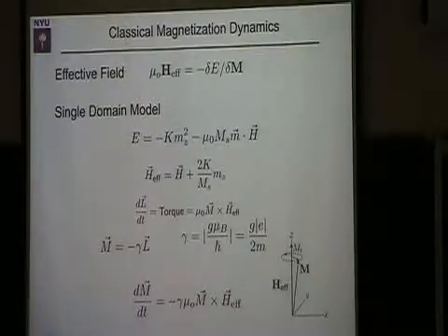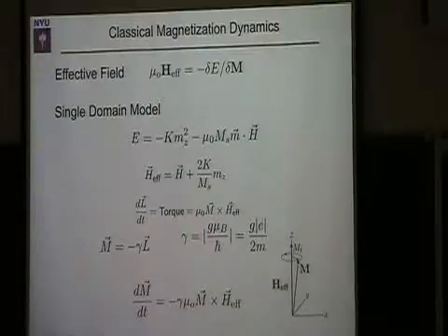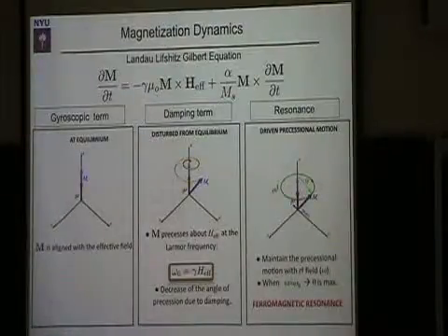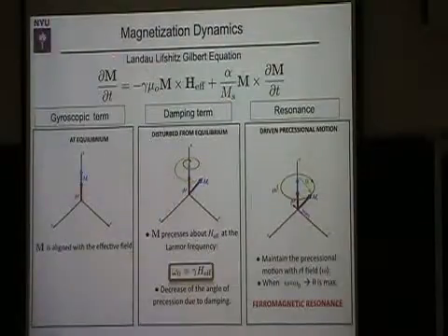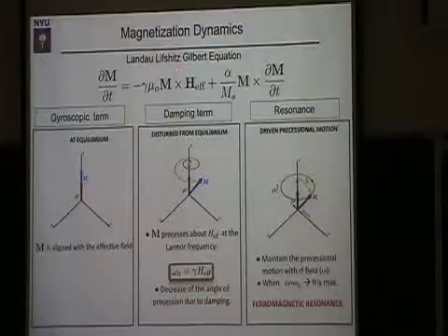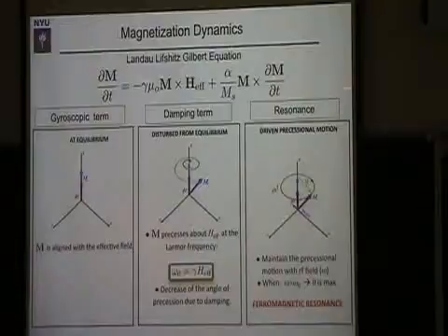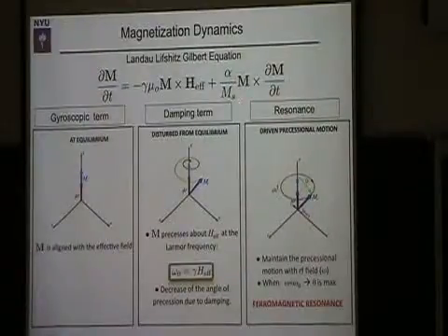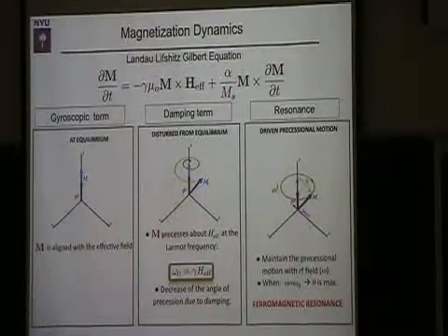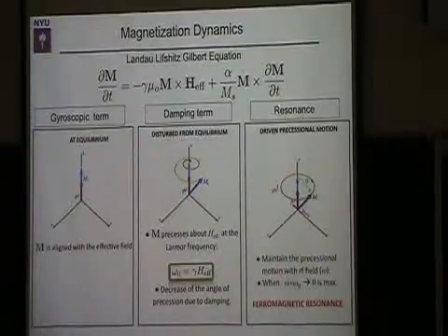It was realized that we also know that magnets come to equilibrium, so we need something else to describe how the magnet actually relaxes, how you get to dM/dt equals zero. This equation was first introduced by Landau and Lifshitz, and they also introduced a form of the damping, some dissipation. I've written down the Gilbert form of the dissipation, which is a viscous dissipation, which says that magnetization decays at a rate determined by its rate of change of a moment.